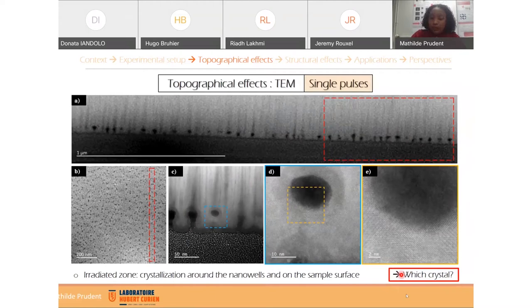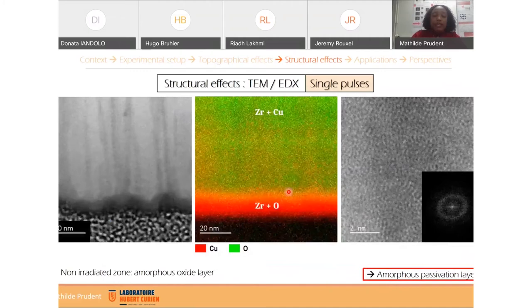So here you can see the EDX mapping on the non-irradiated zone. We can see that the more colored zone matches a zone with a high concentration of zirconium and oxygen. And in all of the sample, we have approximately the same concentration of zirconium and copper as initially. So 65% of zirconium and 35% of copper.